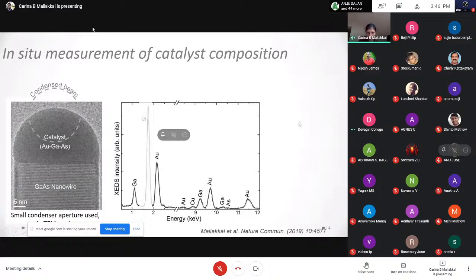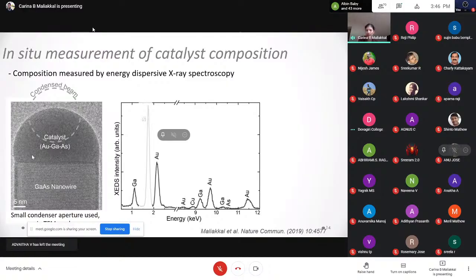We studied the catalyst composition, and we saw that there is a lot of, ignore the silicon peak, it is basically the substrate. And there's a lot of gallium mixed inside the gold, but there's actually very, very little arsenic dissolved inside this catalyst particle. So this is an interesting observation. I won't say it's expected, but people couldn't measure it and show that that is the case. That's it. Okay.